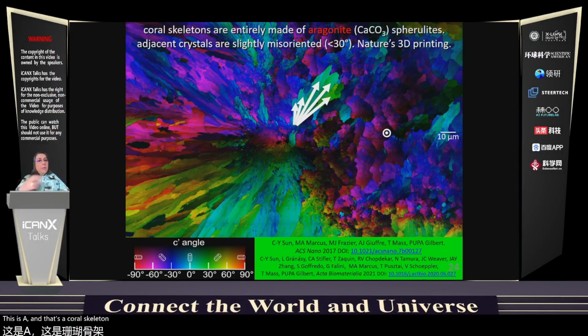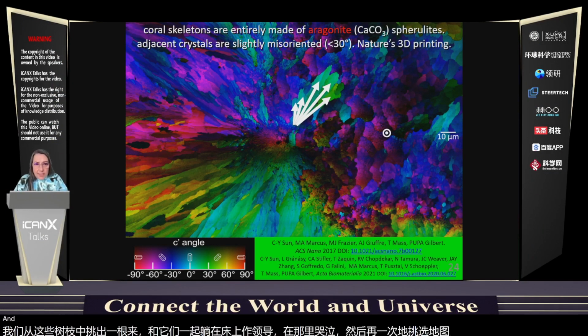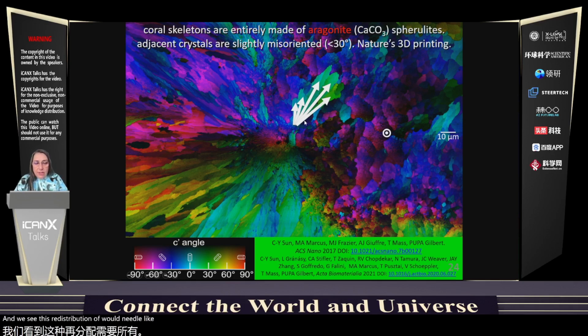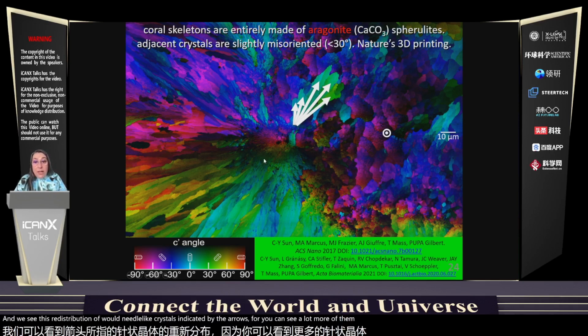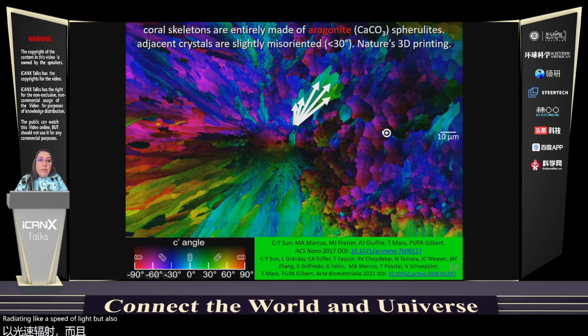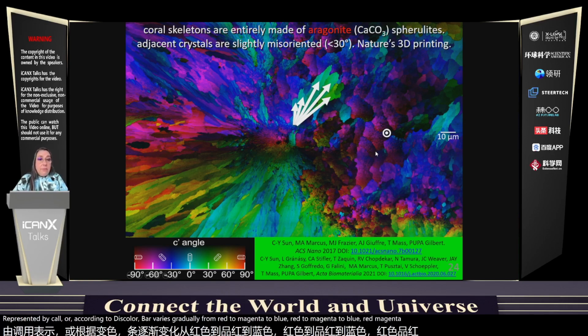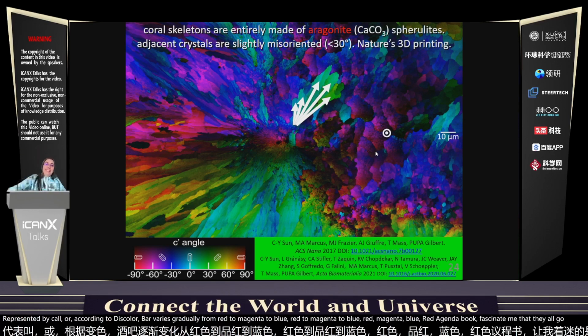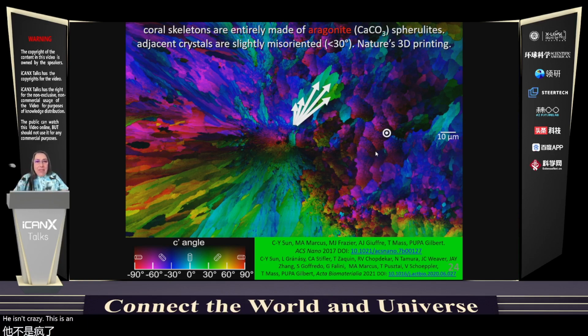If we look at the coral skeleton of aragonite, this is aragonite, and that's a coral skeleton. We take one of those branches, embed it and polish it, and then we image it again with PIC mapping, and we see this distribution of needle-like crystals indicated by the arrows, but you can see a lot more of them radiating like a spherulite. But also when the crystals come pointing at you, perpendicular to the image plane, you can see that the orientation represented by color according to this color bar varies gradually from red to magenta to blue, red to magenta to blue, red, magenta, blue. Fascinating that they all go precisely in the same direction. Isn't it crazy? This is a mad jumble of spherulites in three-dimensional space, and yet there are some regularities which we have not yet fully understood.